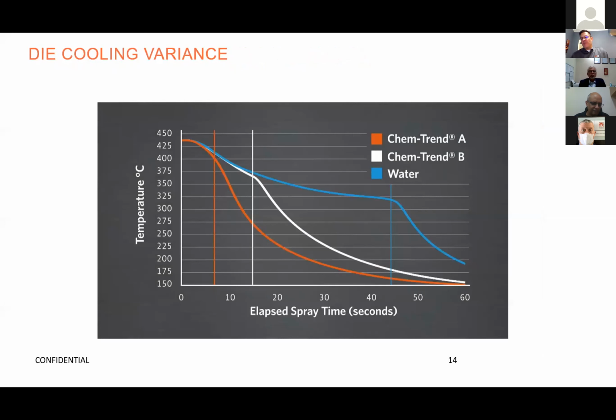So if we come back to the chart, a couple of takeaways from this: there is a difference in chemistry. What you saw there was fully intentional. Typically we're looking for a faster working, higher heat extraction material, but not always the case. If you have some very thin wall castings—say electronics, making cell phones—do we want this kind of heat extraction? Not necessarily. We need to get the film formation, but we don't want to take heat out of these dies.